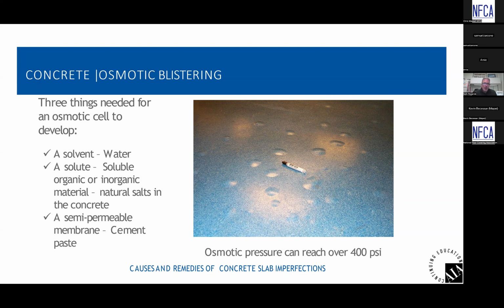And if we have a high salt level at the surface of the concrete, if we have this semi-permeable membrane, if we have a water source, liquid water coming up from the bottom, which naturally is intended to dilute salts. So as that liquid water rises to the surface, and you have that semi-permeable membrane at the surface, could be the pore structure, you can get a head of pressure of water at the very surface as it tries to dilute the salts, and it can't go back down into the concrete. And that head pressure can create pressures that reach over 400 PSI.